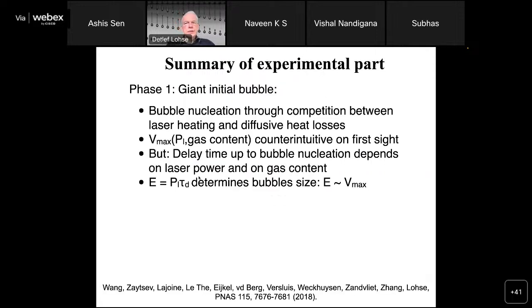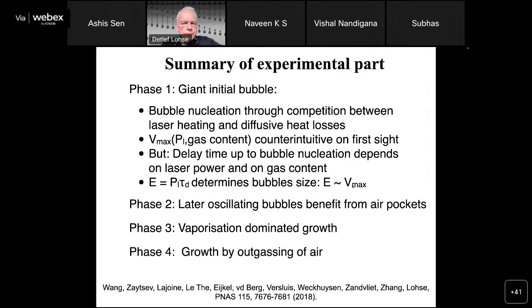So the summary of this experimental part on this bubble. The first phase is a giant initial bubble. You have bubble nucleation through the competition between laser heating and diffusive heat loss. And you get this very counterintuitive result on the maximum volume of this bubble. You can resolve it by calculating the delay time, which determines, in fact, the energy pumped into the system. And then you get this relation: energy pumped into the system is proportional to the maximum volume of the bubble. This is what you expect.